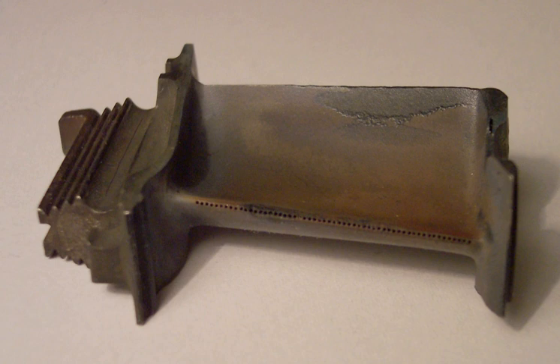Two major types of austenitic stainless steels exist and are characterized by the oxide layer that forms at the surface of the steel: chromia-forming or alumina-forming stainless steel. Chromia-forming stainless steel is the most common type of stainless steel produced. However, chromia-forming steels do not exhibit high creep resistance at high operating temperatures, especially in environments with water vapor, when compared to Ni-based superalloys. Exposure to water vapor at high operating temperatures can result in an increase in internal oxidation in chromia-forming alloys and rapid formation of volatile Cr hydroxides, both of which can reduce the durability and lifetime of the alloy.